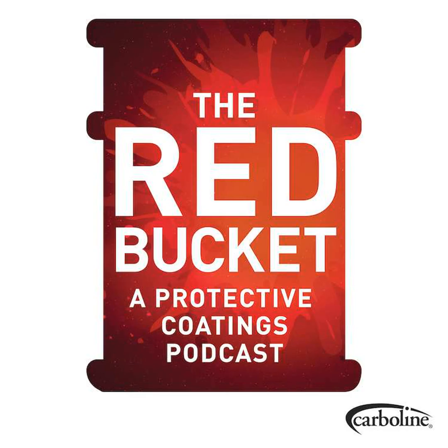So how do these methods compare in terms of adhesion? How durable is that bond in each case? In the case of adhesion over time, we know that galvanizing starts with really, really good adhesion because of that, quote, metallurgical bond. In the case of an inorganic zinc silicate system to metal, we have good adhesion initially, but over time it actually increases. And what we found with galvanizing is that over time it actually decreases.